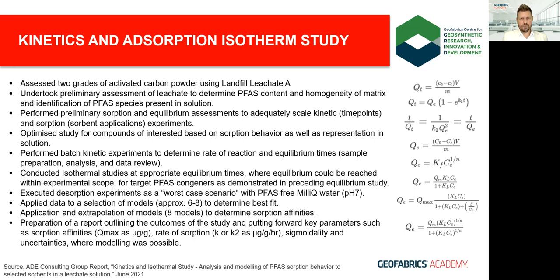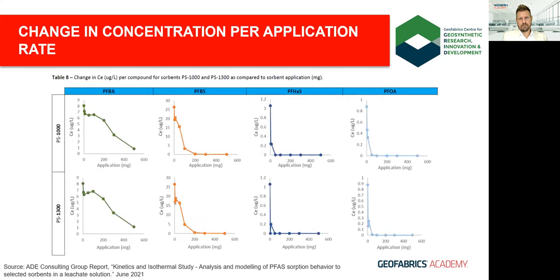The study involved reaction rates, equilibrium times using increasing amounts of activated carbon, and desorption rates using pure water as an index test. The main four PFAS assessed were two short chains — PFBA and PFBS — and two long chains — PFHxS and PFOA — based on having the highest levels in the matrix. Results showed that an increase in amounts up to 500 milligrams addition rate resulted in higher sorption, with not much difference overall between the two grades in terms of mass of solute remaining in solution.